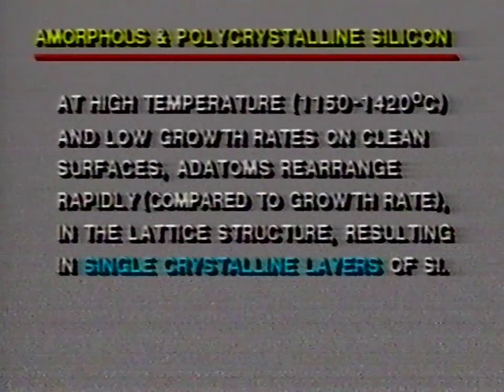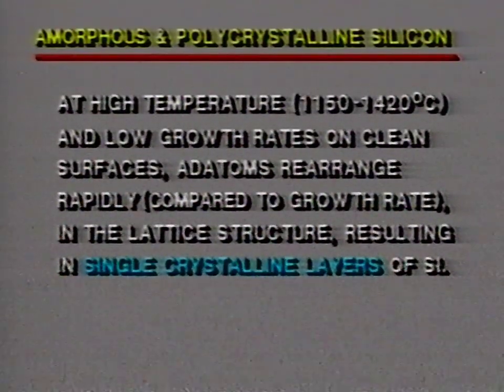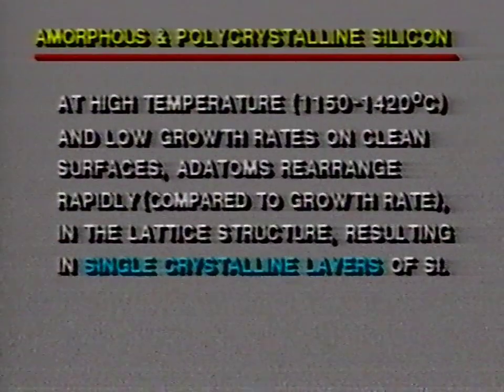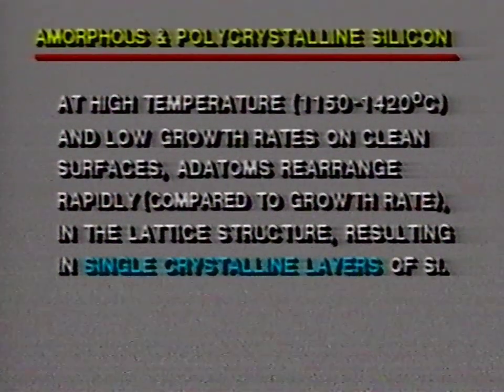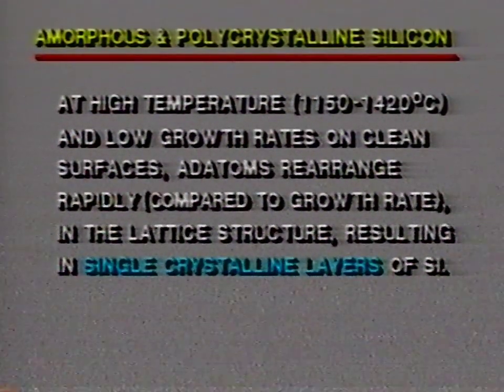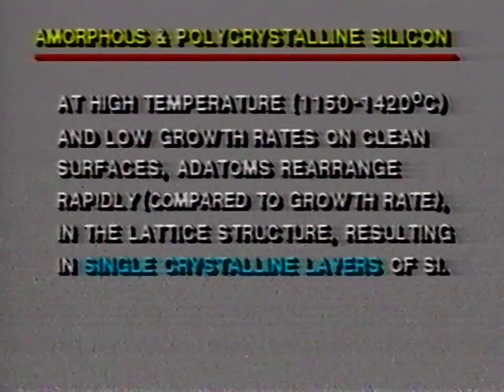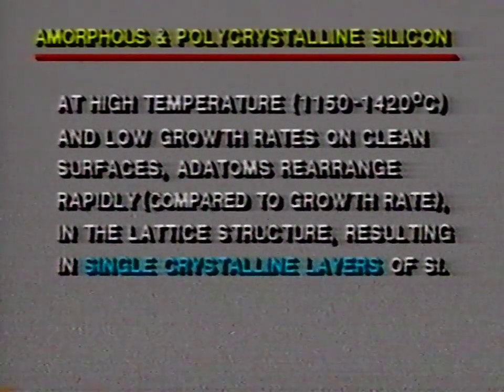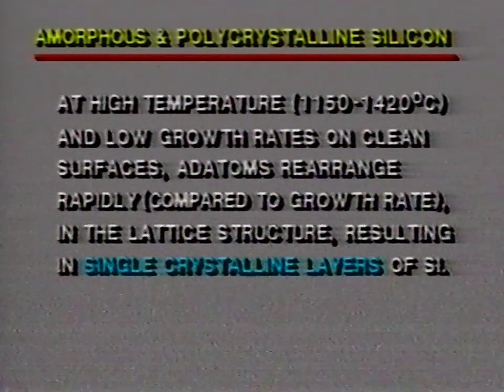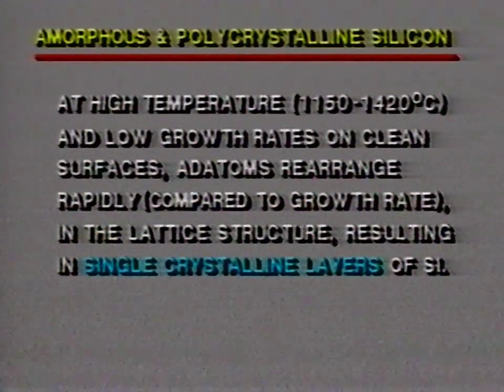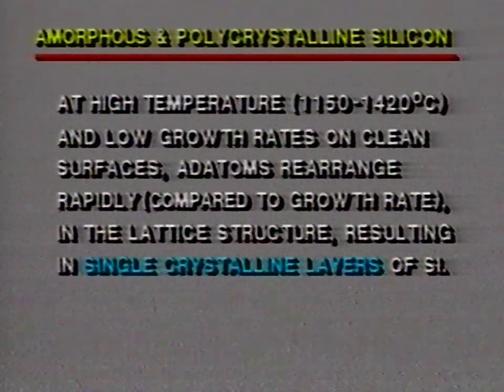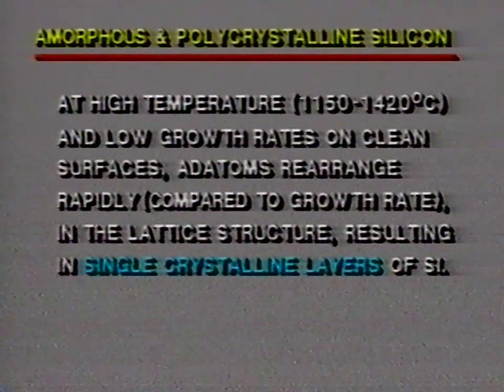Now, if you go to very high temperatures, such as 1150 to 1420 degrees C, and low growth rates, assuming you have a clean substrate surface, atoms rearrange very rapidly compared to the growth rate in the structure that's being formed, and that will then result in the single crystalline formation of silicon films.